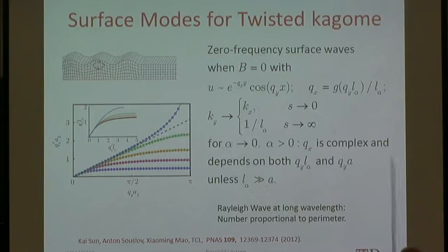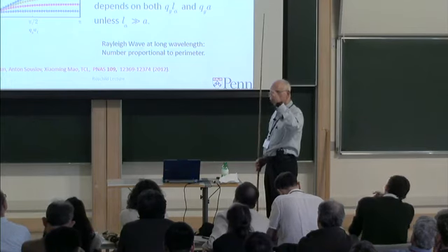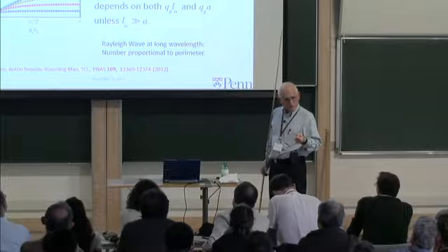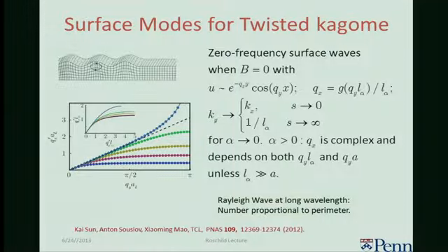So where have the zero modes gone? In the case of the square lattice and the Kagome lattice, when we cut the system, the zero modes of the periodic system became the zero modes of the cut system. In the twisted lattice, we have no zero modes in the bulk, but if we cut things out, Maxwell tells us we have to have a number of zero modes which is proportional to the perimeter. So what's happened? Well, the cut sample has zero modes on the surface, which the periodic or bulk boundary things will not give you. And these surface modes turn out to be, at the long wavelength at least, exactly the surface Rayleigh waves of an elastic medium, which, if you calculate the frequency of the Rayleigh waves, have zero frequency when the bulk modulus is 0.